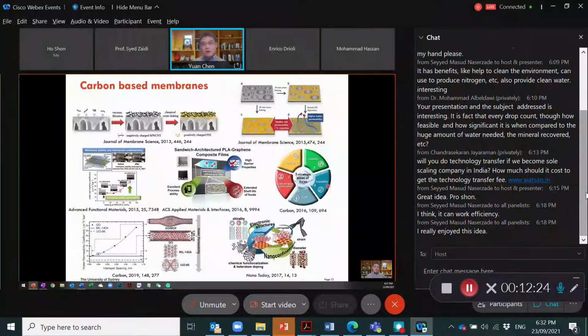So for the membrane area, because I'm actually not a membrane expert, we are carbon material, so the main effort we have is working with the membrane researchers to incorporate the different carbon material into the membrane, because the carbon material do provide the opportunity to tune the membrane properties. For example, for the graphene, recently we have done work using compressed graphene film for organic solvent separation. That do show some advantage because the carbon are much more stable in the organic solvent.